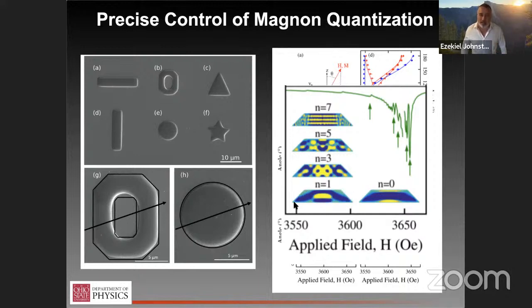And you can see again, the taper of the sidewall here, up to the 7th harmonic, we get very good quantitative agreement with the experimental behavior. So what this means is that we can make specifically the simple structure that we used for that initial theory proof of principle, but we can really make an arbitrary shape for our magnon resonators, magnon waveguides, and precisely predict and engineer what those magnon modes will look like.